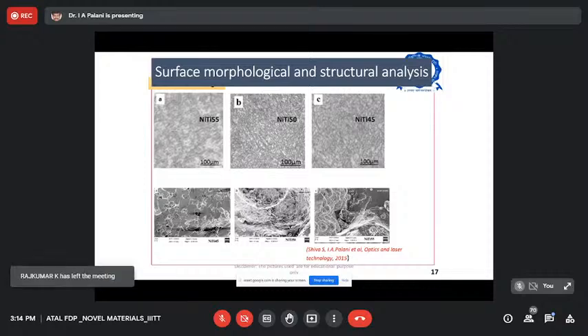So by changing it, we went for different microstructure analysis. We went for a complete mechanical properties analysis. So as far as mechanical property is concerned, we went for micro hardness testing as well as tensile testing to see its behavior. And most important, we went for an XRD analysis. So this XRD analysis will give us clarity with respect to the amount of beta phase which is available. Okay, so this beta phase basically ensures how much shape memory effect is available in the system. So with that, we were trying to look into the beta phase characteristics of it.